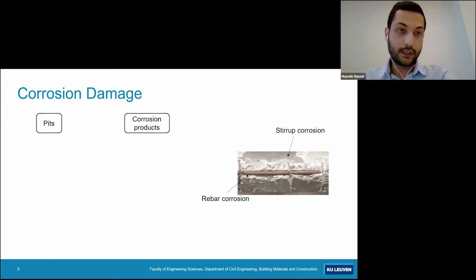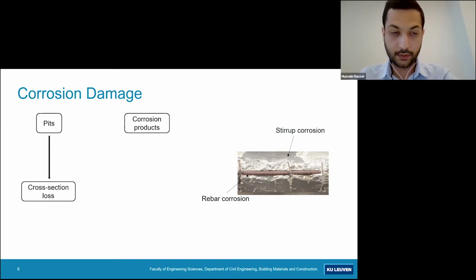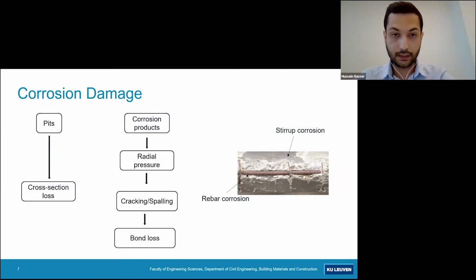In reality, concrete is supposed to protect the steel from corrosion. However, if chlorides come in contact with the concrete and penetrate to reach the rebar, a corrosion reaction can initiate. This corrosion reaction leads to the formation of pits and corrosion products. The formation of pits will lead to a reduction in the rebar cross-section, while the corrosion products will penetrate into the pores of the concrete, causing radial pressure and eventually leading to cracking and spalling.